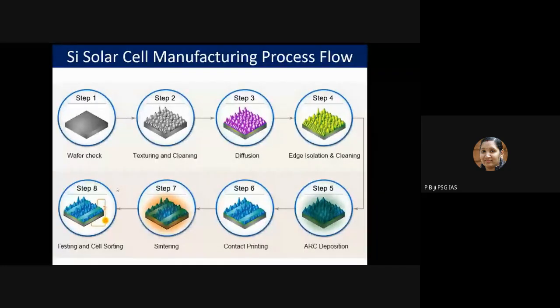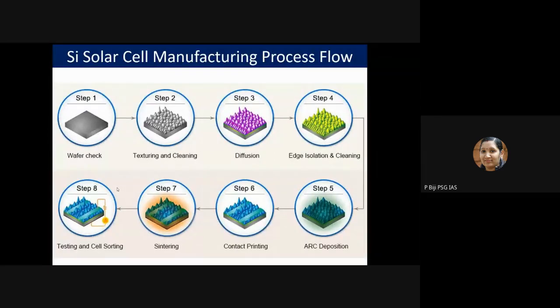After this diffusion process, the next stage is etching, isolation, and cleaning. During diffusion, the N-type phosphorus will diffuse not only on the desired wafer surface, the front surface, but also at the edges of the wafer and on the back side also. This creates an electrical path between the front and back side contacts, which may prevent the electrical isolation between both sides. So the objective of this step, the etching and edge isolation, is to remove this electrical path. After that, the ARC deposition.